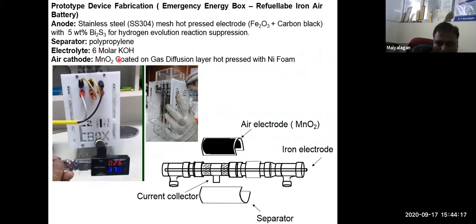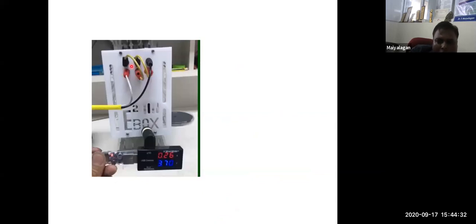We made it with electrolyte 6 molar KOH, and we put MnO2, manganese oxide, on nickel foam. We used this as the air electrode, MnO2, and this is a tubular electrode. We made tubular electrodes, and we put some current collector and made it. And when you look at it,